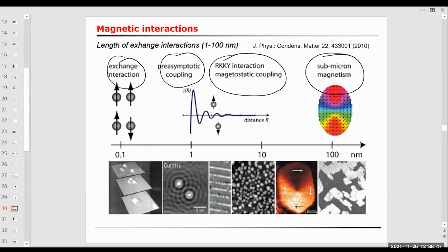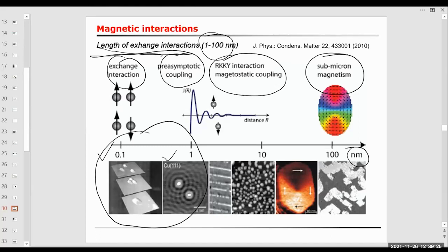If you talk about atomic scale, you can make nuclear spin and nuclear spin interact through another nearby atom, if you are making these materials at this length scale. You see, if I make nanomaterials, copper for example, copper is known to be a non-magnetic material, but if I make copper into nano copper, I can match the dimensions of this nano copper with the length of exchange in copper, and therefore I can even strike some other magnetism, not diamagnetism.